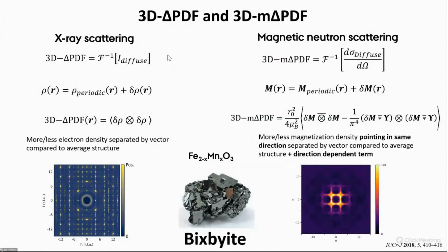Okay, you can do X-ray scattering to get diffuse scattering. You can also do neutrons, and then it gets a little more tricky, because if you Fourier transform your diffuse neutron scattering, then you get the magnetization density. And Nicolai then wrote it all up mathematically and said, okay, if I write the magnetization as a periodic function plus a difference, then the correlation I get when I Fourier transform is this more complicated thing. And now, of course, magnetization is also a vector. But if you're lucky, then you will have no periodic density. So if you have a frustrated magnet, then this goes away. And if you also have a cubic system, this horrible factor goes away. And then you are just left with this one interpreting whether you have